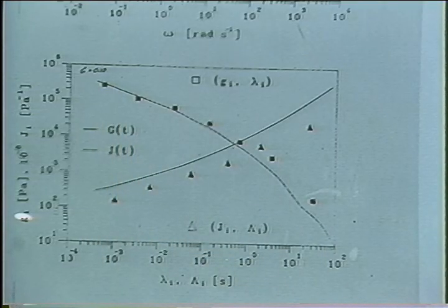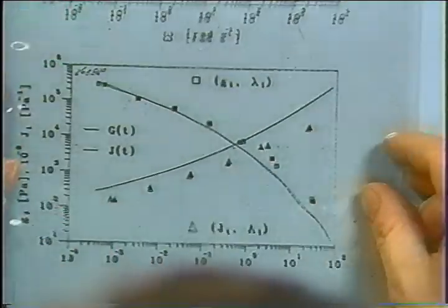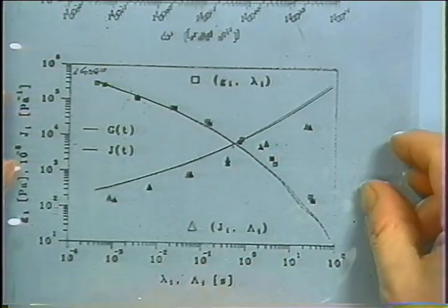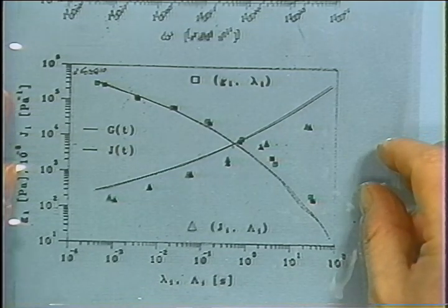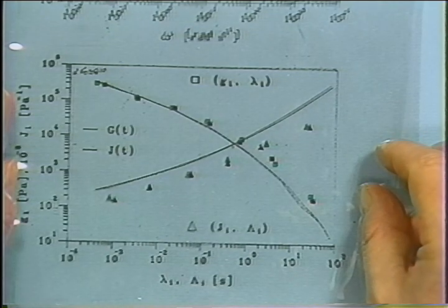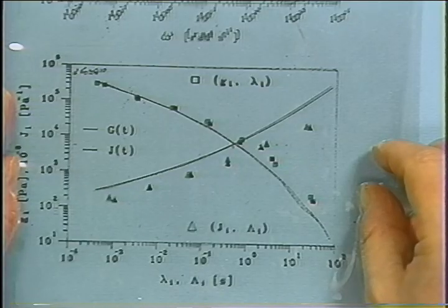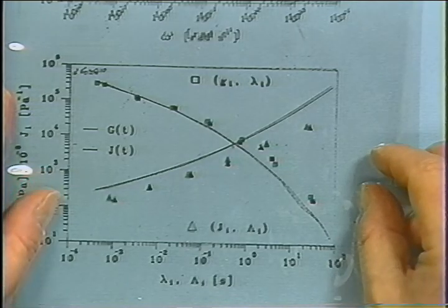In fact, I could take the old spectrum. Here, this is the new one, and I put the old spectrum on top, and you will see hardly any difference. So by fouling up the data with this type of noise, we don't hurt the conversion method very much. It's a robust conversion method. It's certainly not an ill-posed problem.